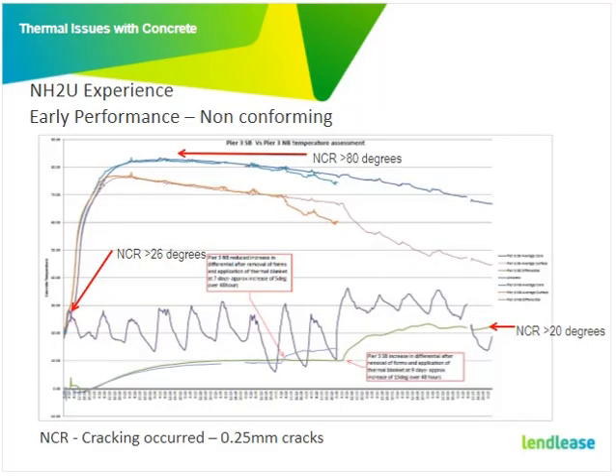So I might go to the next slide. This is the temperature graph for one of the pours, the first pour that we did. And as you can see, we exceeded the 80 degree limitation at the top. That was probably mostly due to our pouring temperature being above 26 degrees.